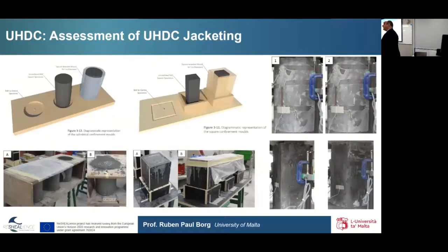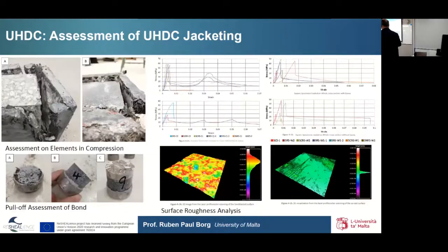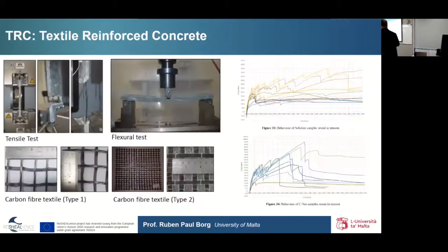The important thing is that we had to retrofit the columns of the tower. So first of all, in Malta, they built a replica, small columns that they jacketed with this material to check the different requirements on the bond between the substrate, the stiffness of the material. These are tests similar to ones that Daniel has shown. So they are tearing off tests just to check the bond level.